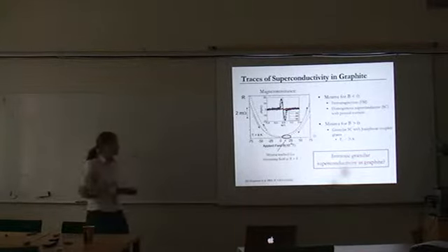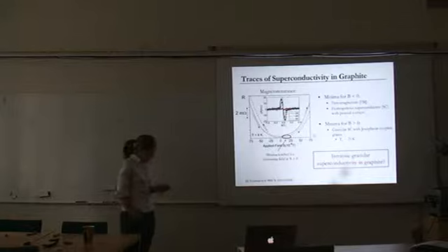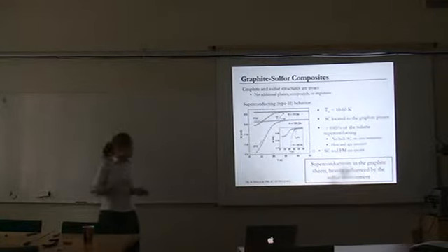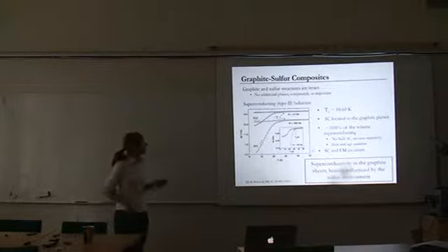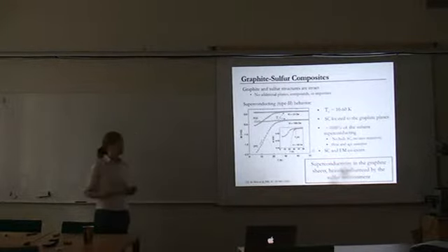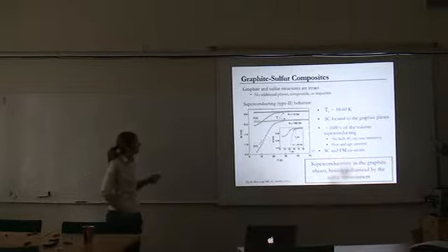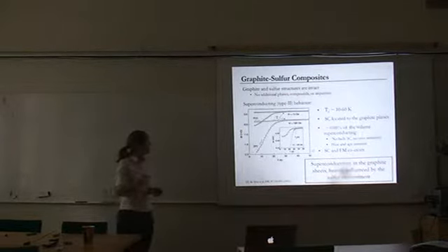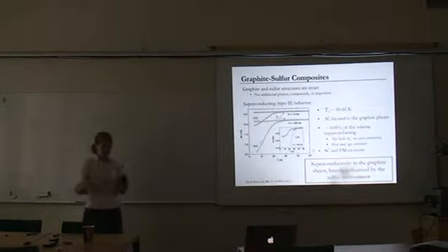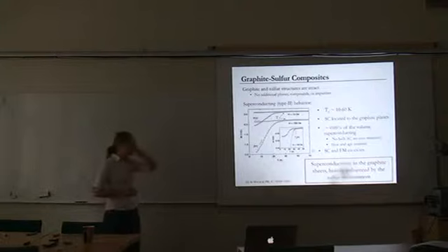So this is in graphite, I should say. The graphite sulfur system is much more solid in terms of its superconductivity there. However, graphite sulfur composites are a rather complicated material. You essentially take graphite and sulfur, and you grind them together. What sort of saves you a little bit is that no one has been able to discover any additional phases or compounds or impurities. It really looks like you have chunks of graphite sitting next to sulfur in these materials, and there aren't any interfacial phases here.